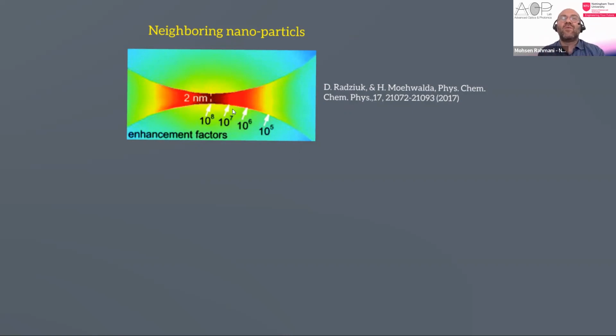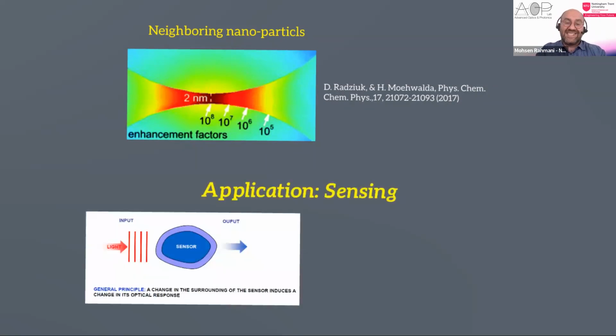In other words, we can confine the light at very sub-diffractive scales in these areas between the nanoparticles. These hotspots and near field enhancement are very sensitive to changes of the refractive index of the environment. That's why this sensitivity makes plasmonic nanostructures very good candidates for sensing, because this sensitivity is so high. So by a little change of the refractive index around the nanoparticle, we can detect those changes and then interpret the existence, absence, or change in the characteristics of the materials around those nanostructures, or sensors in this case.